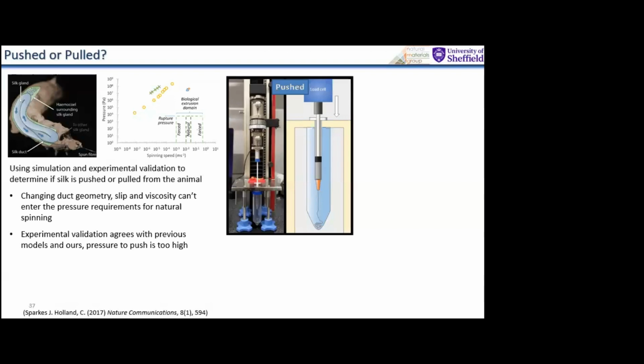The other question is, silk is quite a thick, dense gel. So what is the force required to squeeze a silk out of a tube equivalent to a spider silk? Here we basically took our tensile tester, popped a syringe on it, and measured the force versus the deformation to get a flow rate, and turned it essentially into a capillary rheometer to work out the force required to squeeze silk out of a tube.